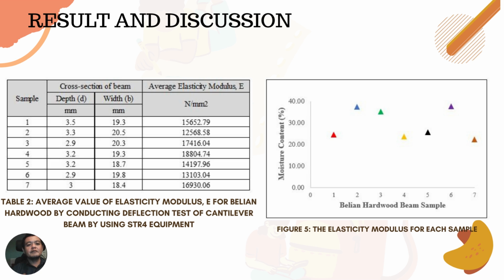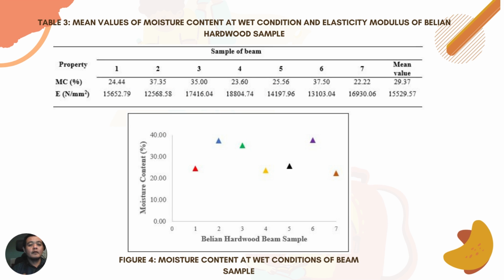Based on Figure 5, the minimum value of Young modulus was 12,568.58 Newton per millimeter square from sample 2, and the maximum value of Young modulus was 18,804.74 Newton per millimeter square from sample 4. The result of modulus of elasticity might be different for each sample because the measurement of each sample is not the same. Table 3 shows the mean value of moisture content was 29.37% and the Young modulus of Belian hardwood is 15,529.57 Newton per millimeter square.